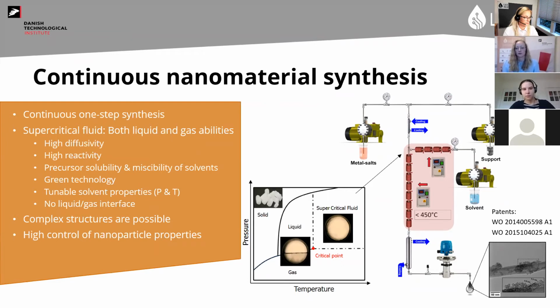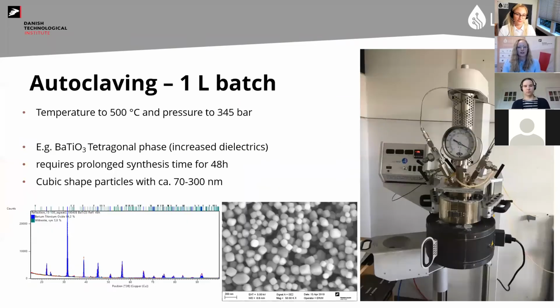So there we have some nice things, but here we have a lower concentration of nanoparticles in the liquid, meaning that we will have more liquid in the end, more nanomaterial in the end to treat afterwards compared to the batch reactor. So if you don't need the very, very narrow size distribution, the batch reactor is sometimes the better choice. Then the final step is kind of like a mixture between the batch and the flow.